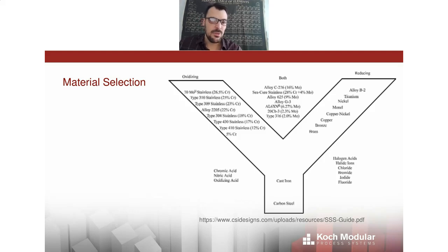out there. So carbon steel is probably the most common metal used in petrochemical process systems, but if it is corroded by the contents of the reactor, we can go to successively higher and more expensive alloys. Now, as we go upwards on this diagram, up the right side, this is the side that's going to be higher in nickel, ultimately culminating near titanium at the top. And this is very appropriate if you have halide acids, hydrochloric acid, hydrofluoric acid, hydroiodic acid.